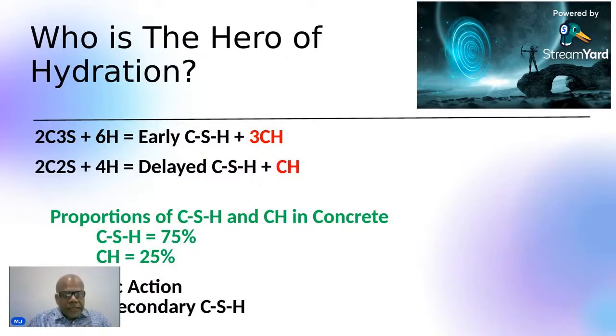So how many voids are there? You see CH is 25%. So out of your total cement paste hydration, total CSH hydrated gel, 75% is good CSH gel, 25% is calcium hydroxide. This calcium hydroxide leaches out over a period of time, from rainwater, from your curing water, even humidity present in the atmosphere. It leaches out and leaves pores inside our concrete.